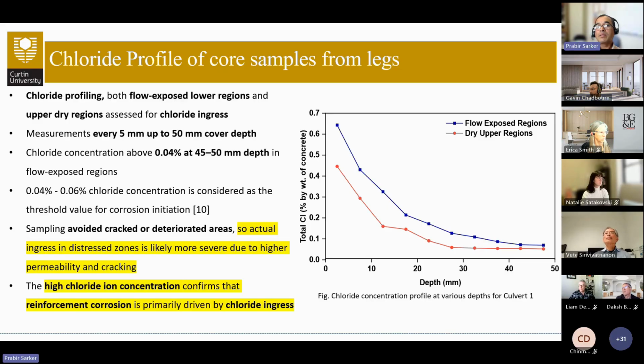Is Liam meaning air content of the concrete cast in the lab, or air content of the culvert concrete? Of the repair mortars that you tested in the lab. And the reason I asked is that SBR is known to cause a problem with air entrainment. I did a lot of work with it in marine concretes many years ago, and that was one of the big problems they had.